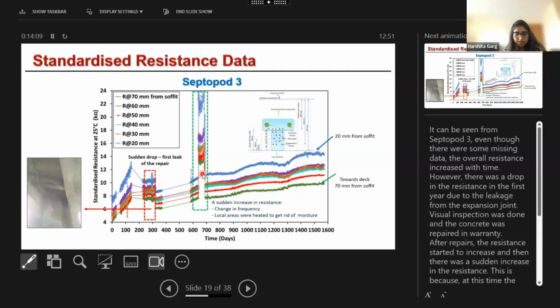Then there was a sudden increase in resistance, the reason for which is still unknown, but two possible reasons were identified. First, during this time there was a change in the frequency of data collection. The data was collected every 2 hours, and then we changed it to twice a day, so that may have messed up the system, giving some inappropriate results. Also, the local areas nearby in the bridge were heated up to get rid of some excess moisture, which could also have led to the increase in resistance, but the actual reason was unknown. Overall, the resistance was increasing. The resistance was higher near the soffit, due to water vapor evaporating through a breathable coating, and it was lower near the deck surface.